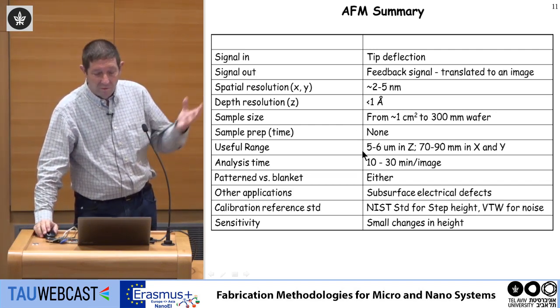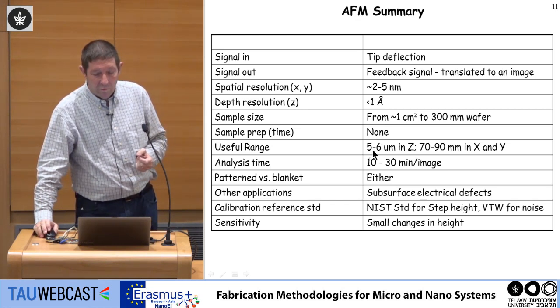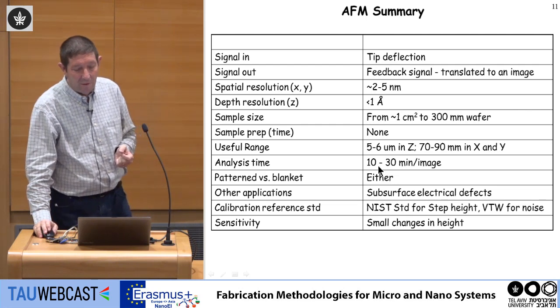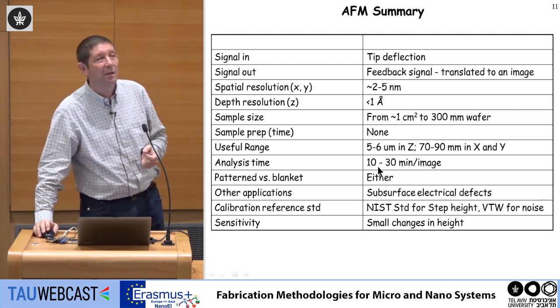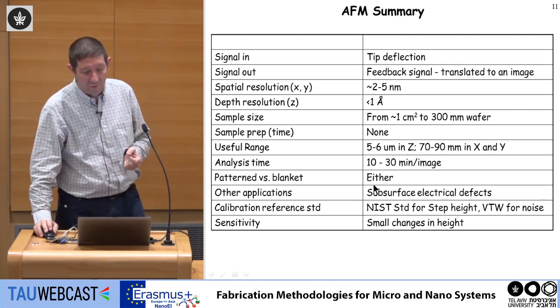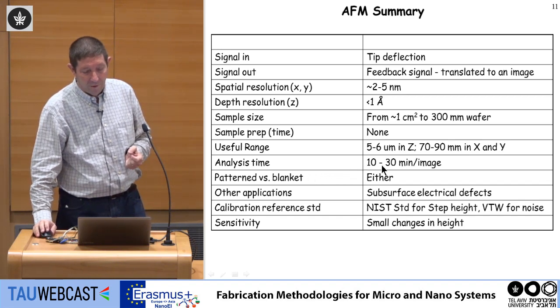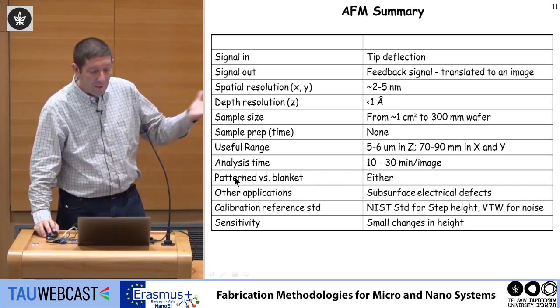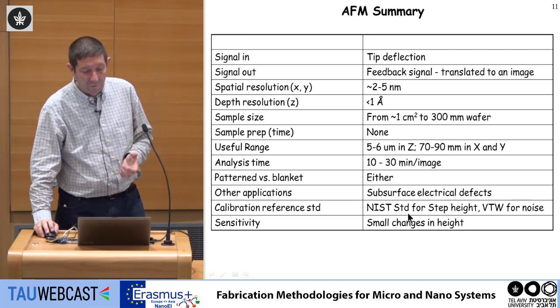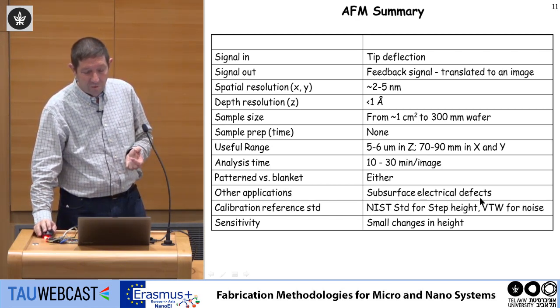Sample preparation is minimal. You can go 5 to 6 micron in Z, 70-90 mm in X and Y. This is the total range. Time is typically a few minutes, 10, 20, 30 minutes per image, so it's slow. You can work on pattern wafers, you can work on blanket wafers, and other applications, subsurface electrical defects.